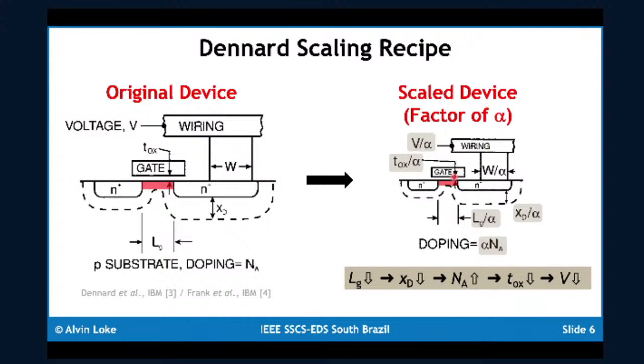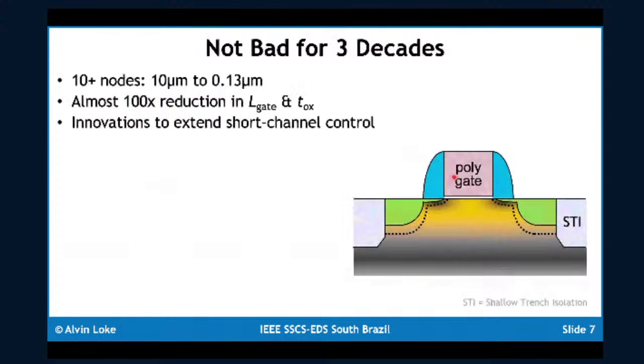So this has been essentially the recipe, the blueprint for our industry for about 3 decades. It spanned from 10 microns to 130 nanometer, where we had essentially 2 orders of magnitude reduction in gate length as well as oxide thickness.